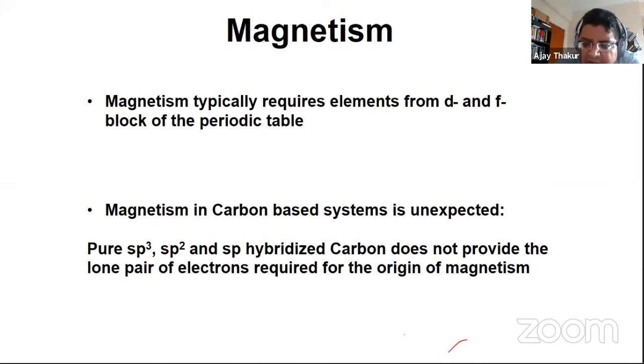However, of course, science progresses or technology progresses via leap of faith of individuals, and indeed we witness 2D material, some of the story which I would be telling. So in addition, magnetism typically requires elements from D and F block of the periodic table, right? And magnetism in carbon-based system is therefore unexpected because this is purely an S block element, and pure sp3, sp2 or sp hybridized carbon does not provide the lone pair of electrons required for the origin of magnetism. So whenever there was any experimental signature, even pre-2000s, there have been several reports where people have observed magnetic behavior in carbon-based materials. It was simply ruled out, saying that it must be due to some kind of an impurity.